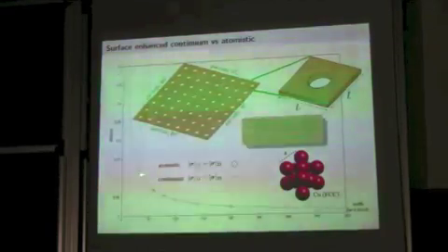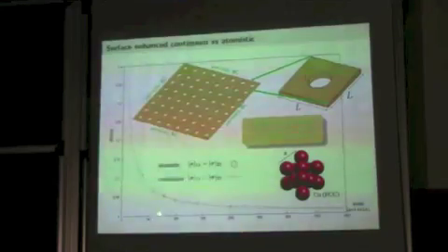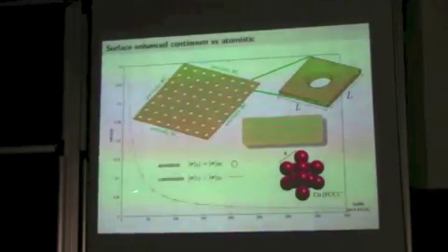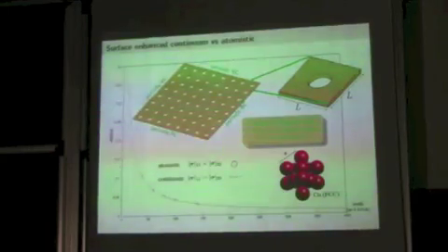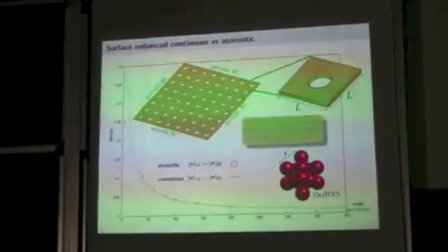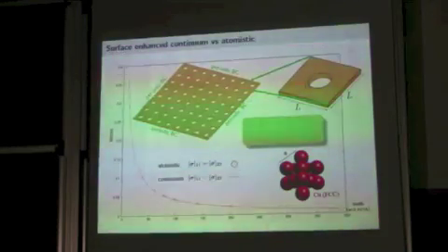But the more interesting is when you are at smaller size. So this is when you have like 40 unit cells. You see already a little deviation. If we want to go smaller than that, we may see even more deviation, but it's even more than just a deviation, because if you go smaller, you cannot really rely on your zero thickness assumption of the surface. So the whole theory becomes quite questionable, I think. And I think this would be my view on why I need these higher gradients and what I do here. So I think after this relatively long motivation, I could get to the talk.